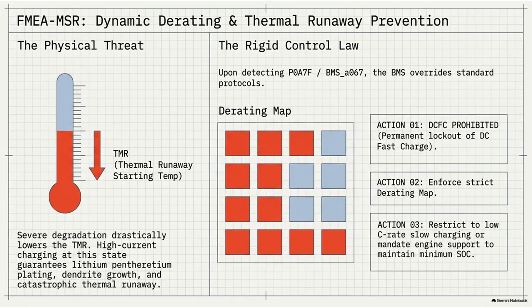Yes, and a pierced separator results in an instantaneous, hard internal short circuit. Which is terrifying. The ensuing massive current discharge localized at the puncture site generates catastrophic heat, immediately pushing that degraded cell past its lowered thermal runaway threshold. Which is exactly why the BMS permanently locks out fast charging, because the calculus proves the structural integrity required to safely absorb that current no longer exists. It is a non-negotiable functional safety mandate.